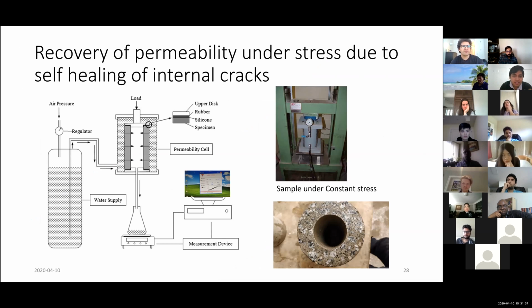So after all these tests, I switched to observing recovery of permeability under stress. This is a setup that was developed in the lab previously. They have a water tank, and we supply air pressure into this tank. This drives the water under a fixed value of pressure, and the water goes into this system. So this is my specimen. This is the hollow cylinder that we can see here.